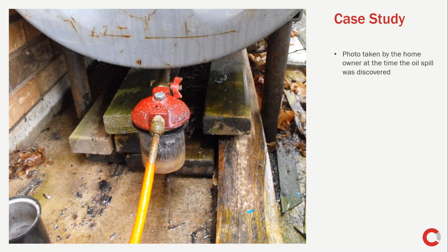At first glance, you think that the bottom of the filter here is actually still attached, but really that's not the case. This bottom is actually a block of ice, and the filter covering is on the bottom left here. So it's a little bit of a tricky image. And this was an important picture for the investigation because soon after, the weather changed and this caused the ice block to melt, which would have made determining the cause much more difficult.